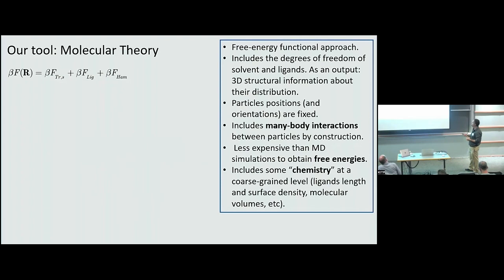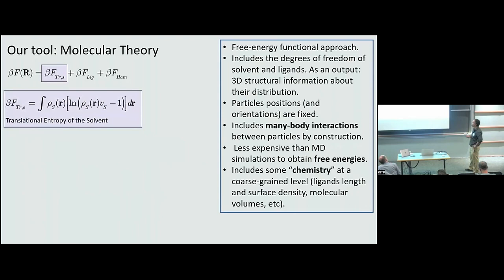In this particular case, this free energy is very simple, it has only three terms. So, for example, the first term is the translational entropy of the solvent, so the solvent is there. And it's important to note that this is done for nanoparticles that are fixed in space. The inorganic core behaves like a hard solid, so the solvent cannot enter, the ligands cannot enter in that region where the inorganic core is. And then the ligands and the solvent are treated in a mean field way between the particles, right? And, for example, in this particular term, there is this function rho s, that is the density of the solvent in each point of space. That's something that a priori I don't know what it is, so you need to calculate, you need to find that. This is an unknown, okay?